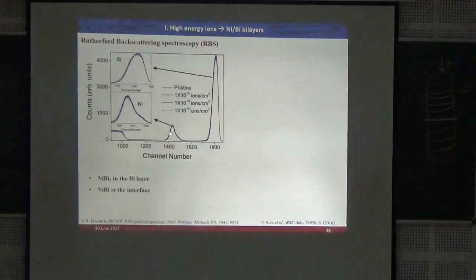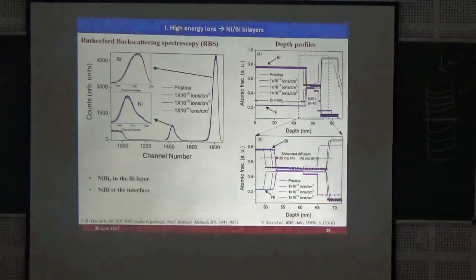This is the bismuth peak, this one is the nickel peak, and this one is for the silicon substrate. After fitting these RBS data using RUMP simulations, we can get the depth profile, the atomic fraction as a function of depth.